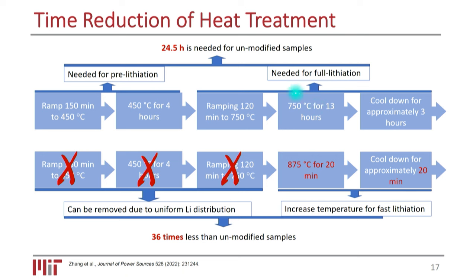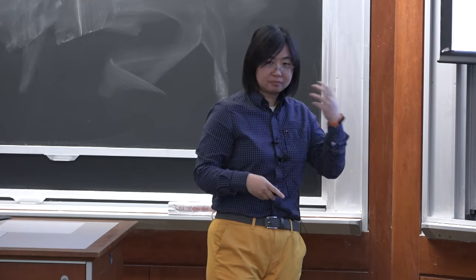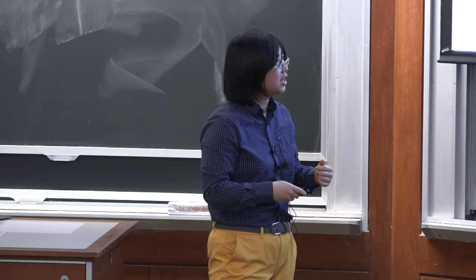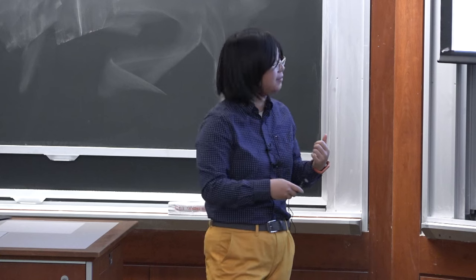Actually, in order to not crack the particle and also make a uniform distribution inside the particle, we need a relatively long time of ramping up the temperature. And the total process actually takes a day. But with our method, utilizing the FASP method as well as adding 2% of urea, we can eliminate all these processes. And by just putting the particles into the oven for 20 minutes, we can get the end material. So ultimately, we are achieving 36 times faster synthesis. You can imagine how much cost and energy consumption this is going to save.